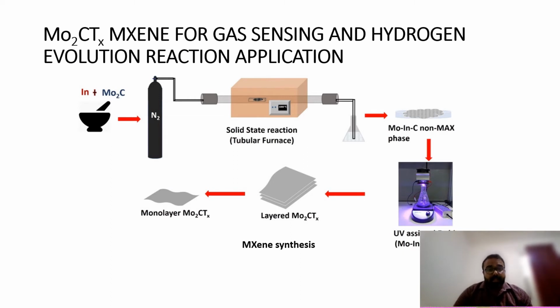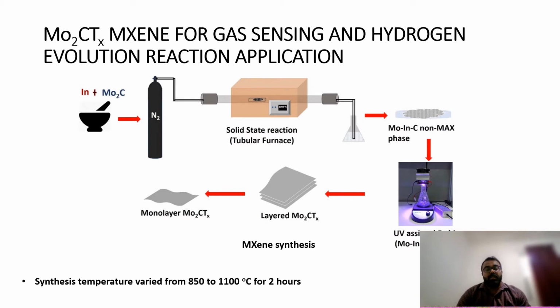In our study, the MXene synthesis was attempted by first making the parent non-MAX phase. For that we used indium and molybdenum carbide as the precursors in bulk form. They were crushed and ground using a mortar and pestle to make a uniform powder mixture, which was transferred into an alumina crucible. We did calcination, or heat treatment, which is also known as a solid state reaction, a physical method, inside a tubular furnace. We varied the synthesis temperatures from 850 to 1100, and the reaction time was fixed at 2 hours. We made 3 sets of samples at 850, 1000 and 1100 degrees Celsius.